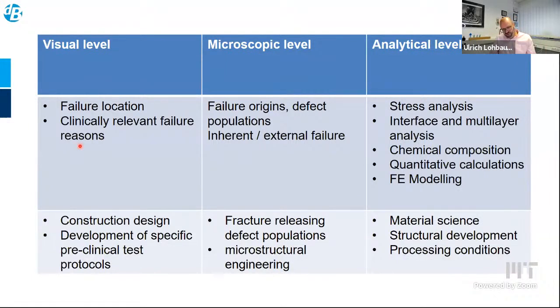For example, in dentistry, we are having the problem that the surfaces are ground during insertion of the restoration, and this grinding induces defects, and this is a kind of failure reason that is easily identified on such a surface. So we can use it for recommendations, we can use it in construction design, but we can also use it to see what's wrong clinically.